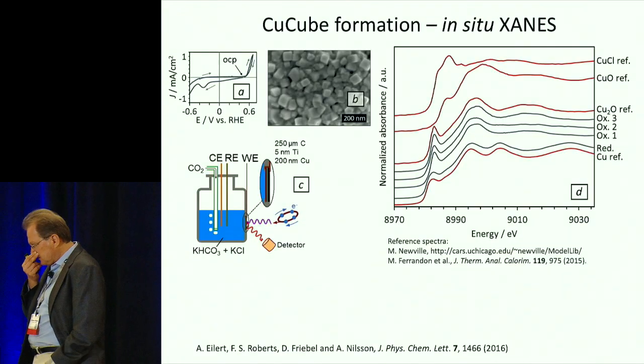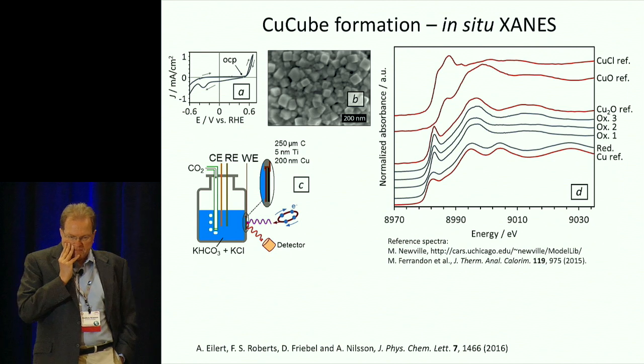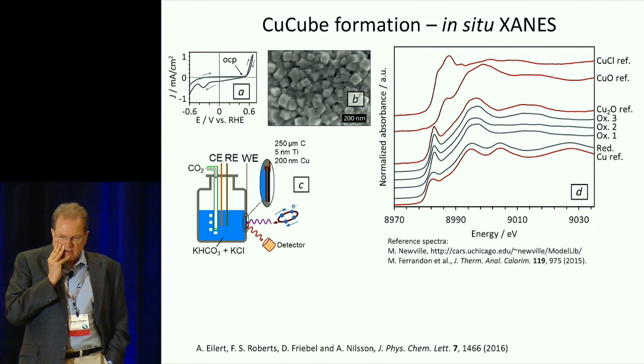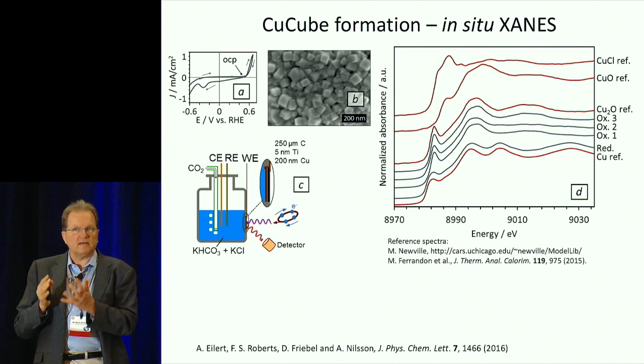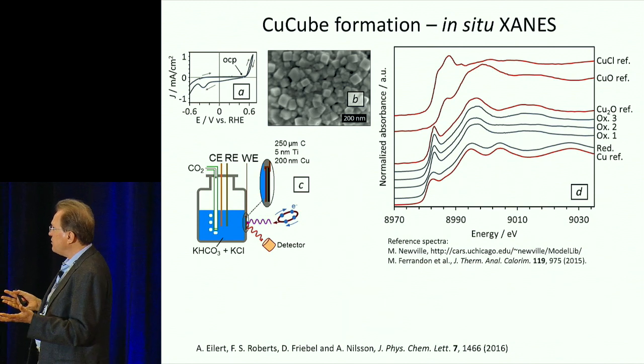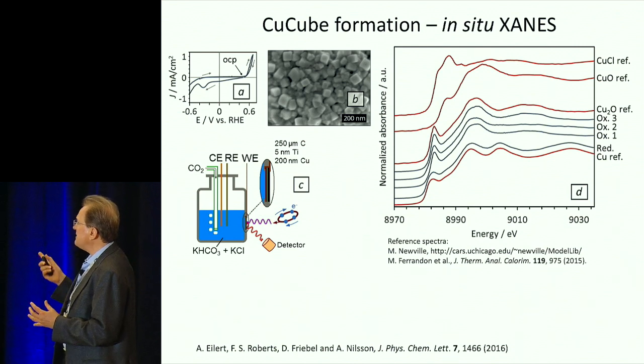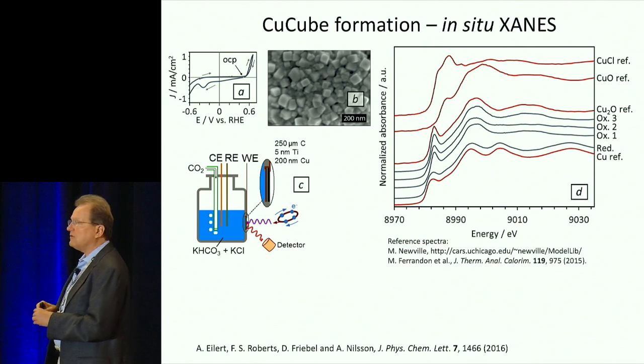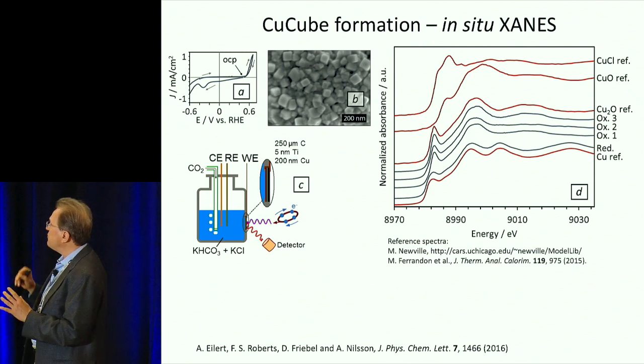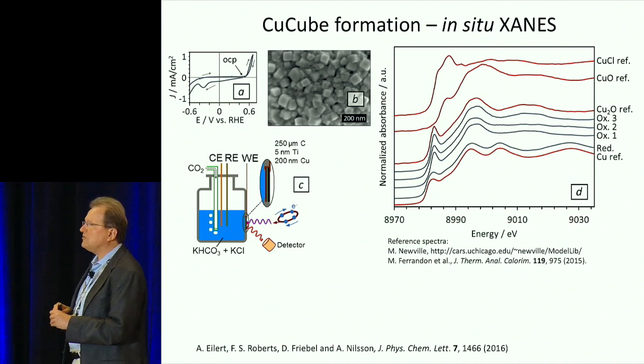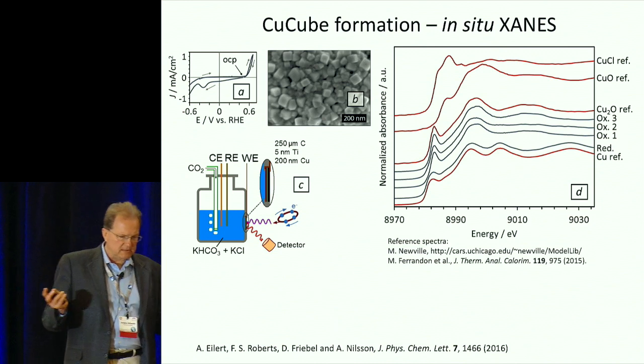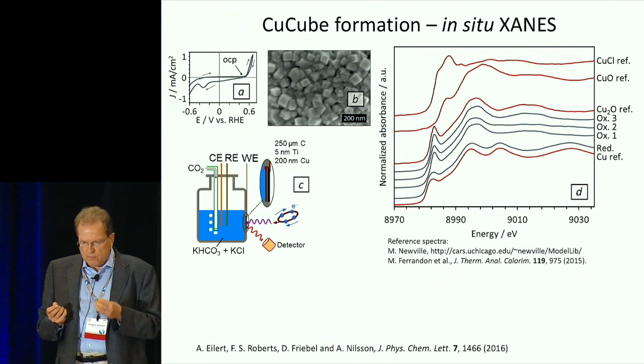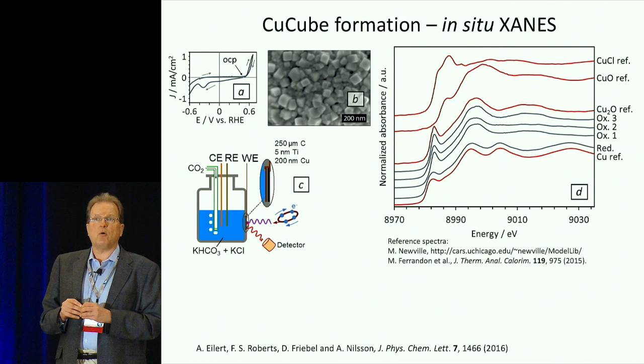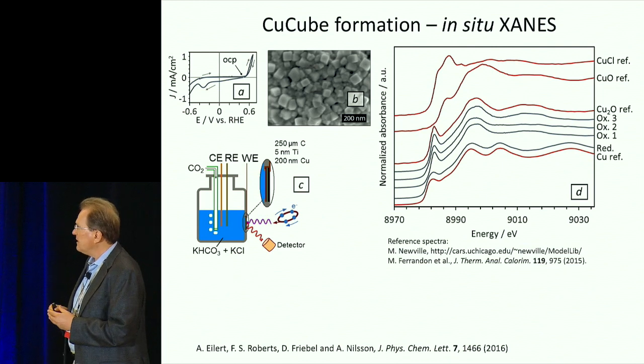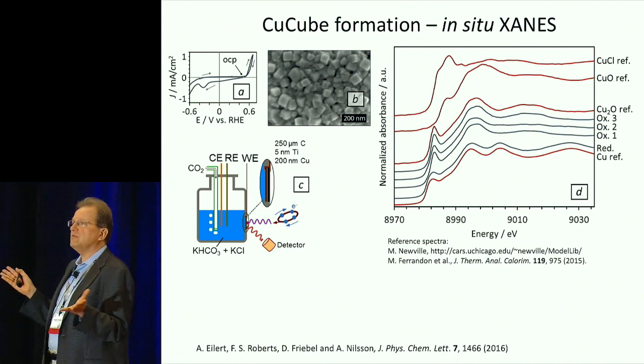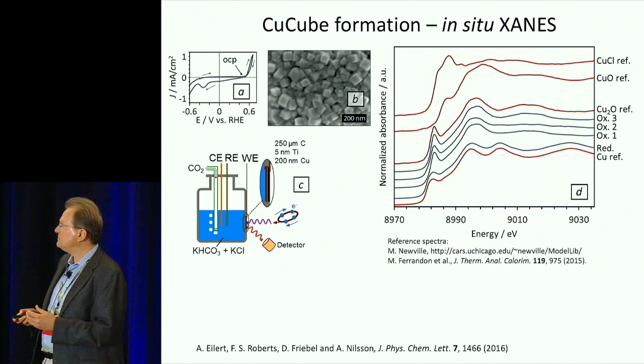And this, of course, opened up the question originally: what is this caused by? Are we forming some sort of copper chloride precursor that is actually being reduced? That's maybe why it looks very cubic. And we went to SSRL and did in situ X-ray absorption spectroscopy measurements of the copper K edge. I don't have too much time to go through all this in detail, but what we found was that no, there is no copper chloride being formed. Instead, it looks like copper(I) oxide is being formed under oxidation conditions, and then you reduce that, and the only thing you see is metallic copper.